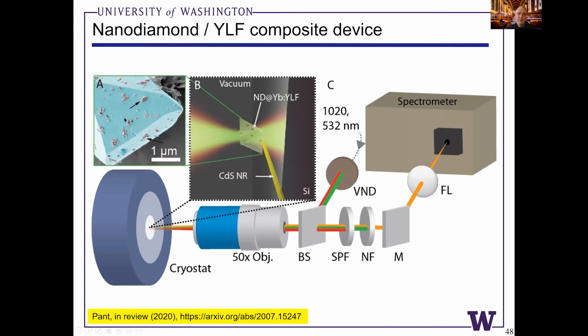So what we've done more recently is we've taken these ceramics. These are yttrium lithium fluoride ceramics doped with ytterbium, and we've coated them with amorphous nanodiamonds. These are milled HPHT diamonds that we've color-coded red. I don't know how well it comes through in the slide, but these are very bright, very nice materials that we can get ODMR signals from, and NV emission, very bright NV emission.